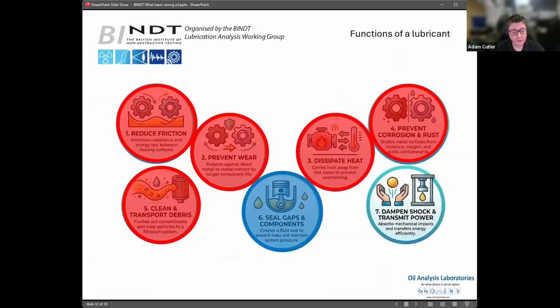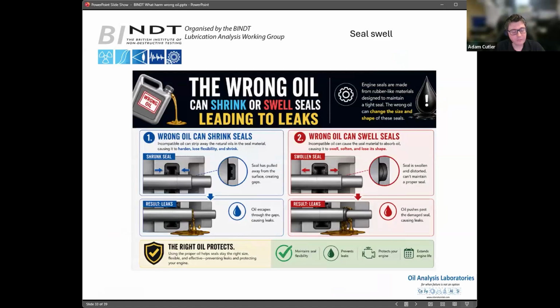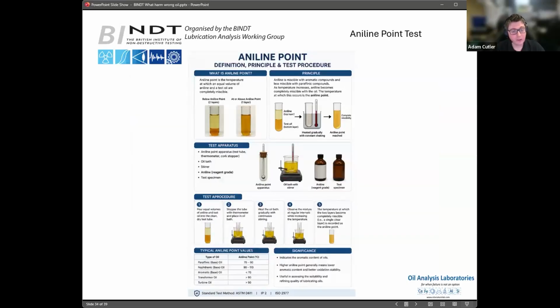Lubricants are also required to seal, as I mentioned before. So a common issue you have is when switching from one brand or one type of oil to another in large lubricated systems, you can lead to shrinkage or swelling of seals, which lead to them not seating right in the housing and leading to small leaks throughout the system. And this is one of the things when you're switching in very large oil systems and large lubrication systems, is to actually check for seal compatibility. So some of the ways you can do this is you can measure an aniline point. So you can measure the inherent aromaticity of the products, and this will give an indication of how well and how compatible the oils will be.